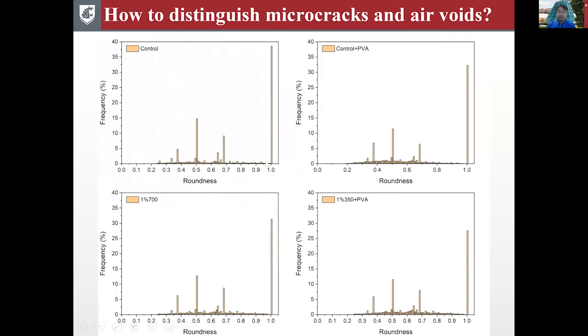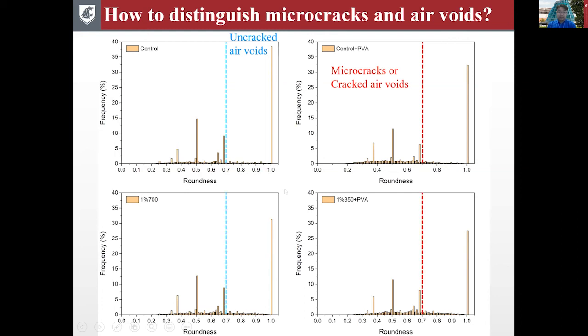So after collecting the information of all the voids, we can have a histogram of the air voids here. It's easy to determine the threshold of 0.7 for the uncracked air voids, and for the voids with a roundness smaller than 0.7, we can define them as micro cracks or cracked air voids. And similarly, as we can see here, there's an even distribution of voids from roundness of 0.35 to 0.95. They are actually the microcapsules. And similarly, we can categorize them into broken microcapsules and unbroken microcapsules.